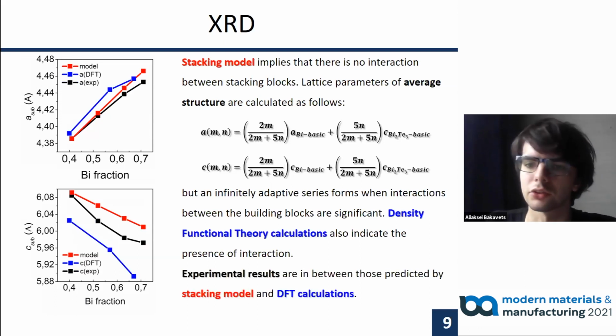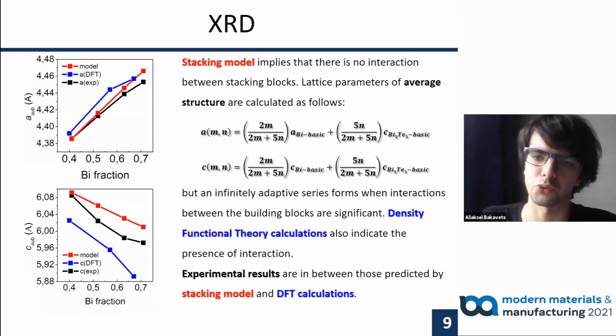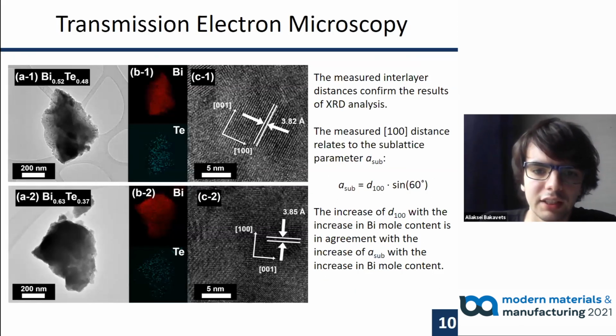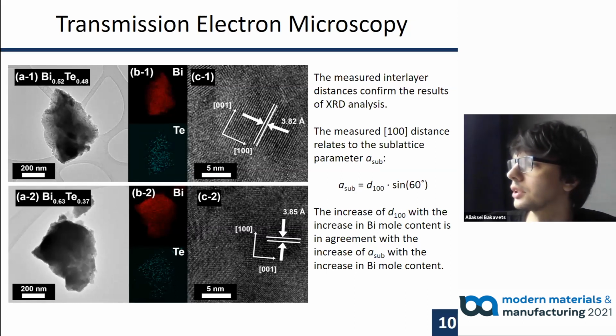Our experimental results fall in between those predicted by density functional theory and the stacking model, thus indicating the interaction between the building blocks of the superlattice. The refined lattice parameters were in agreement with the microscopy data as shown in this slide.